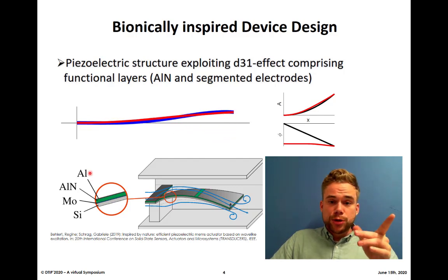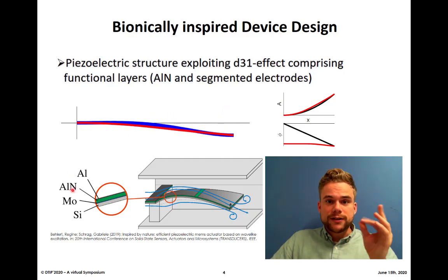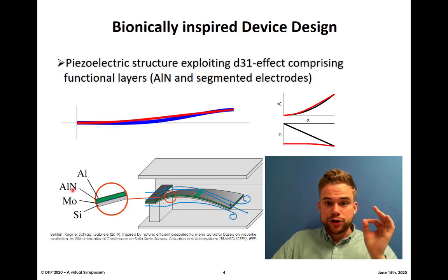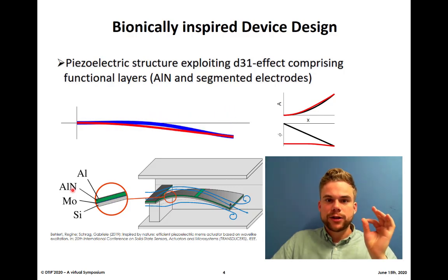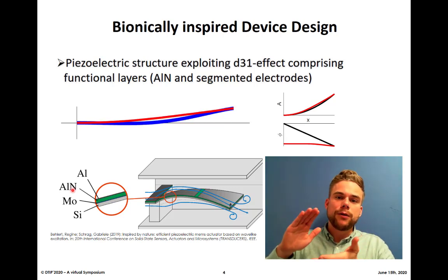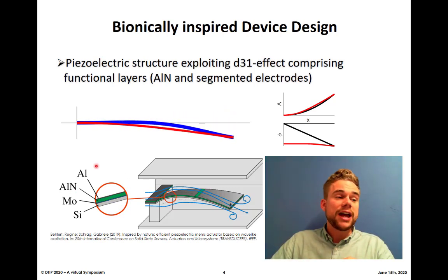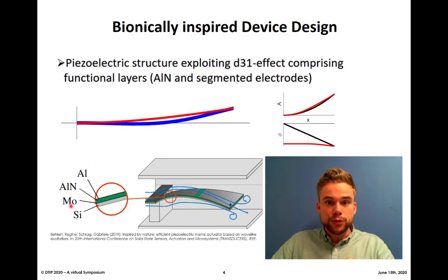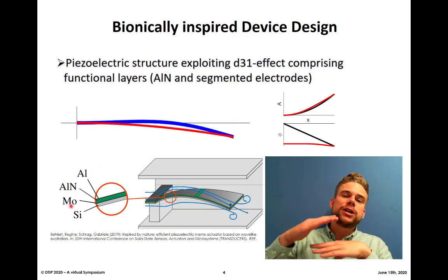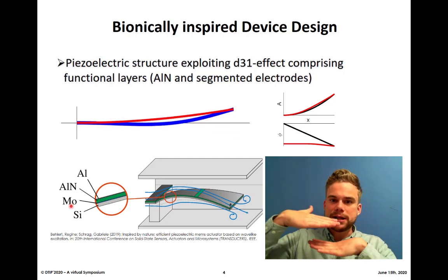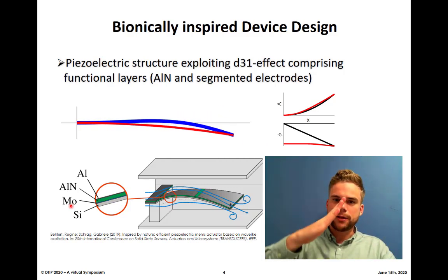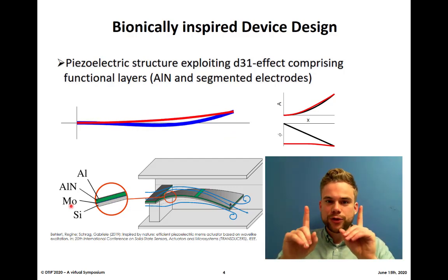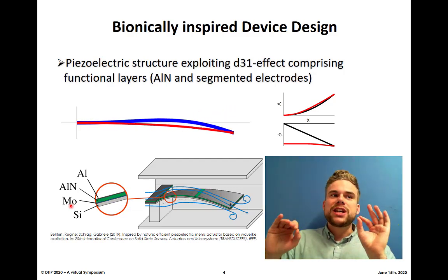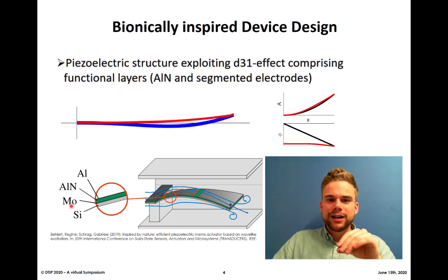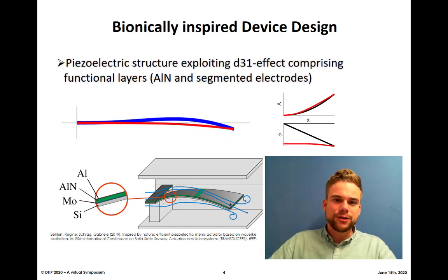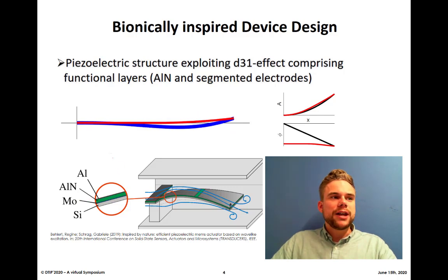We use aluminum for the electrodes, aluminum nitride as the piezoelectric functional layer that is using the d31 effect by applying a voltage between the aluminum electrodes and the molybdenum electrodes below that aluminum nitride. We create through the d31 effect a bending that is basically doing something like this, and since we're doing that on both electrodes with a phase shifted signal, we can kind of approximate this undulating movement, and you see that in the red line here.